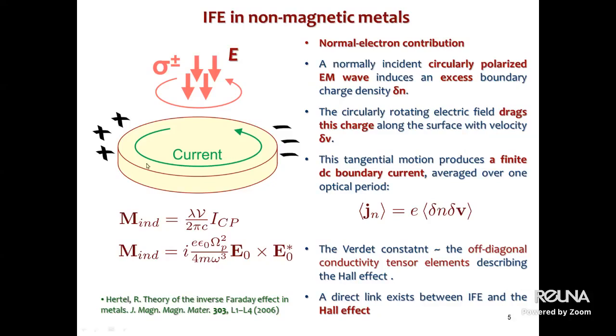The Verdet constant, which is V here, quantifies the inverse Faraday effect, and it's basically a constant of proportionality between light intensity, which is the intensity of circularly polarized light, and induced magnetization. It can be derived from the off-diagonal conductivity tensor describing the Hall effect. To this point, I will come a bit later. So basically, there is a direct link between the inverse Faraday effect and the Hall effect.